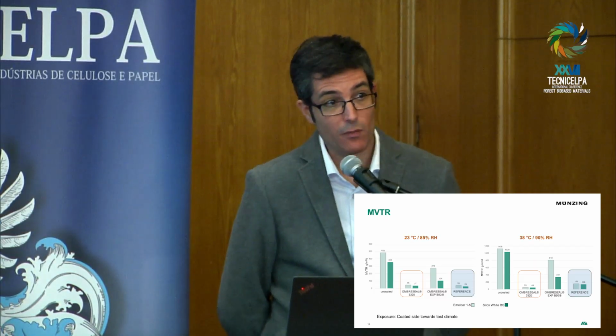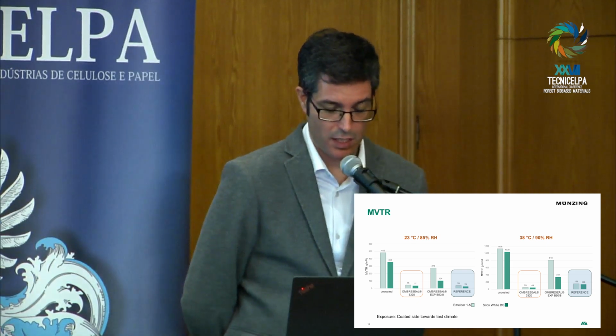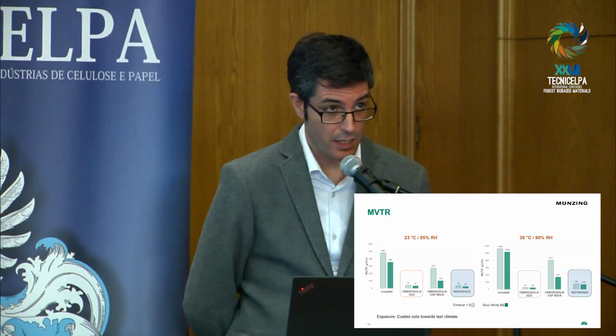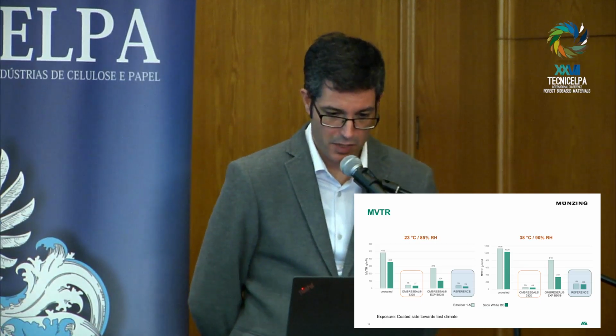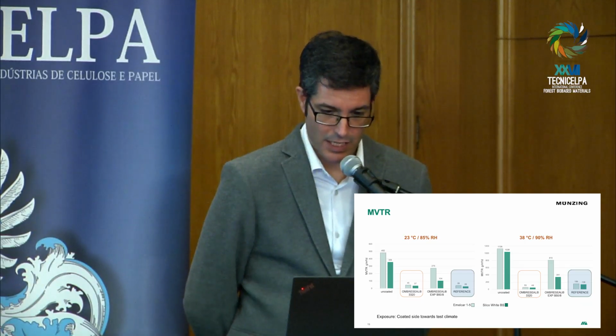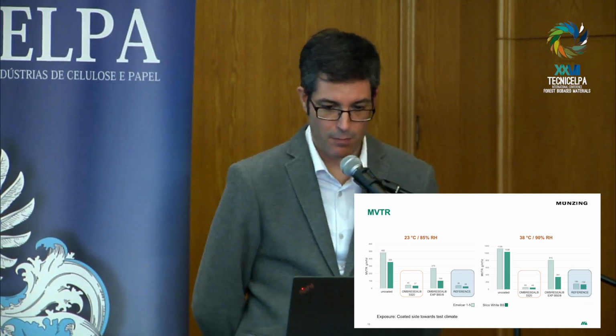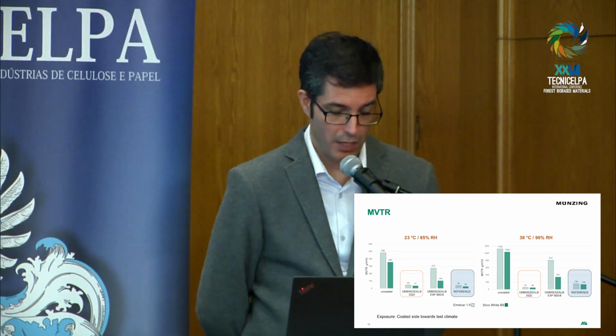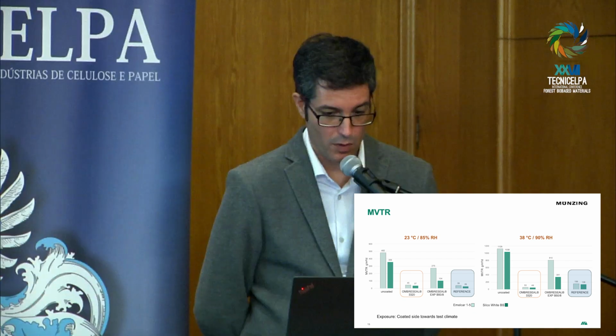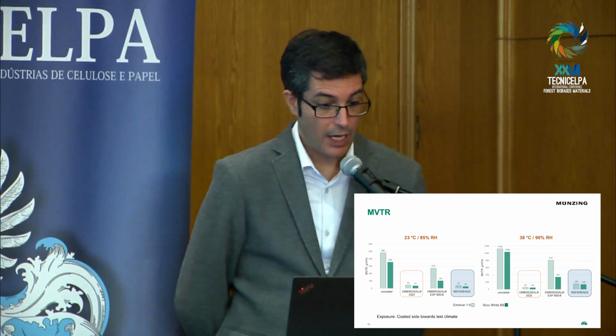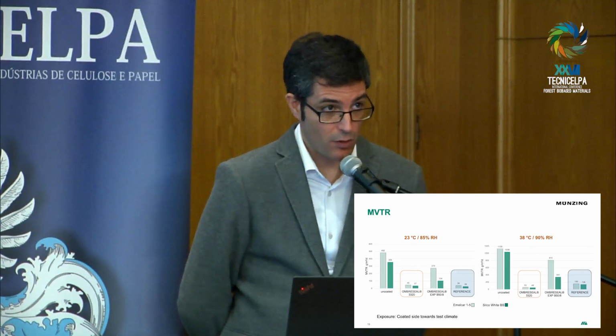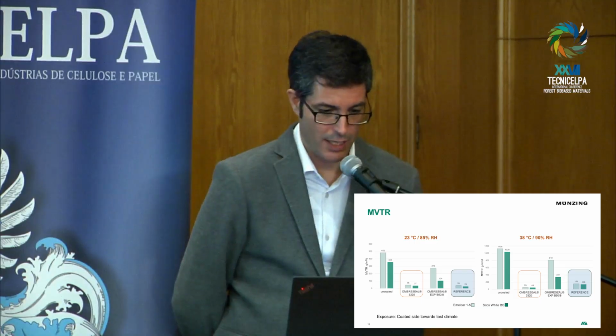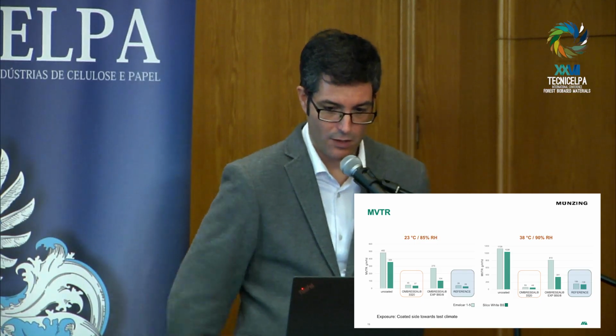It is even more surprising when we jump to the tropical conditions, because you can see here the absorption of both papers is much higher. In both cases, we exceed 1,000 grams per square meter a day. With the Ombrasil XP 50/8, we reduce it significantly, especially with the pre-coated material, and the reference gives us some really nice values, 150 and 140. But it is even more surprising that the Ombrasil 3320 reduces by 1/3, more or less, the values that we got with the fossil-based material, which is really impressive, I would say. Just to clarify, we expose the coated side to the atmosphere toward the test climate, because that way we better control the absorption of humidity on the paper.